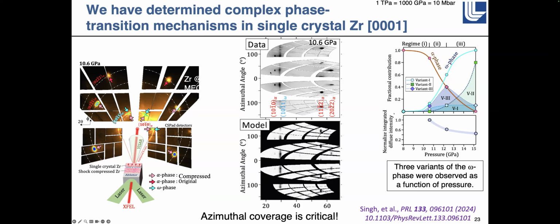It splits into some very sharp spots, but not in the same orientation as we started with, and they're not all the same orientation. So we get several different orientations, but we can actually see what the texture of the sample is, and it turns out that it's essentially a twinning process, where we compress the material and it twins. And then the omega phase, we started to see diffraction from that. It's also highly textured, but we only saw one peak, and we should have seen five or six peaks out here in 2 theta. It wasn't until Suransh Singh, who was the first author on this paper, interpreted it.